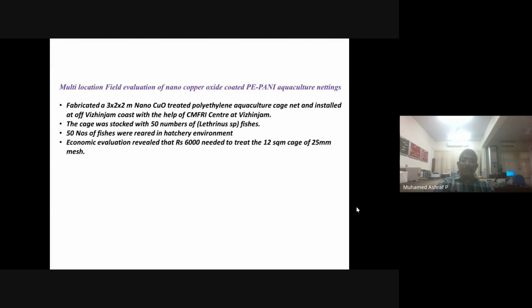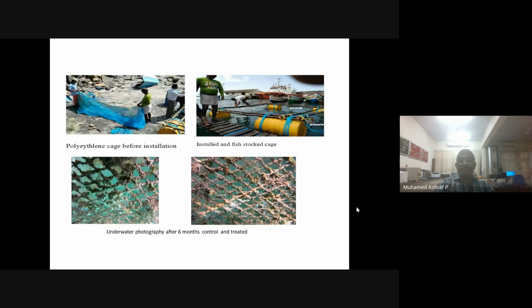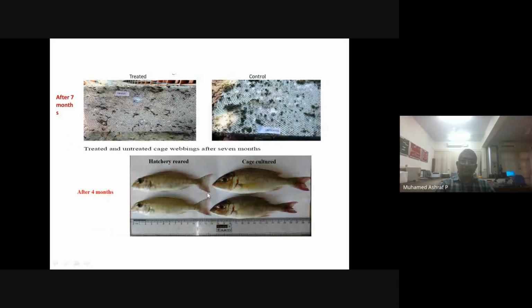And then we have done a small work on multi-location field trials. We prepared aquaculture cage nets, treated and untreated, and made cages and exposed them to the marine environments of southern Kerala. We can see that the coated cages show comparatively good biofouling resistance compared to the untreated one. And then we grew fish in them. You can see the difference. This was kept at the same time in a hatchery, and this is the cage culture one.